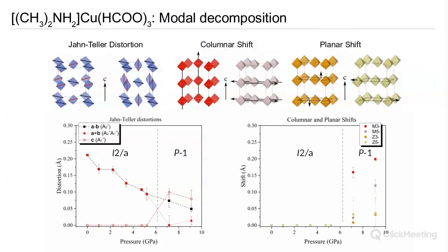system. We can then look at the Jahn-Teller distortions. Now, we can consider these to be conventional, essentially. These would be allowed in the inorganic case. And again, there is clearly a striking reconfiguration of the Jahn-Teller distortions. And on top of this, what you can tell with the black line here is that we have this reconfiguration, but we also have a global reduction of the Jahn-Teller distortion. So it is responding in a similar way to the potassium copper fluoride. We do see a reduction in the amplitude of this mode, but we still have this very large reconfiguration that occurs at about 6 GPa. And then we can look at the columnar shifts and planar shifts. These, again, are unconventional modes of the lattice with respect to the inorganic. And we see very much that these switch on in the triclinic phase.